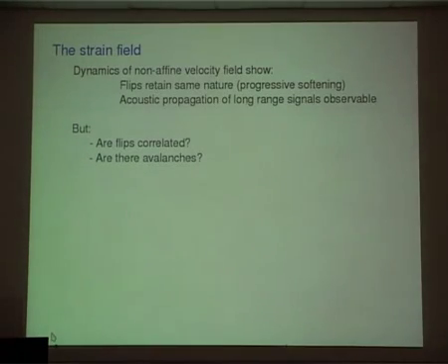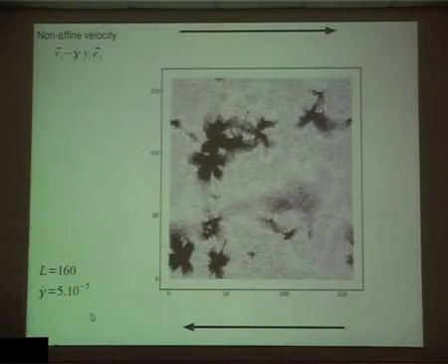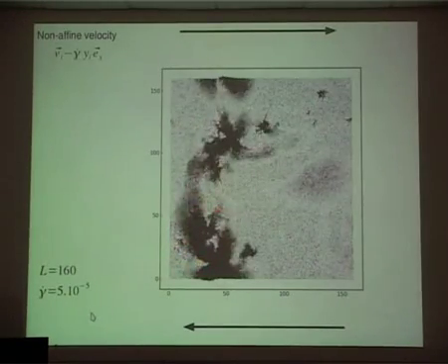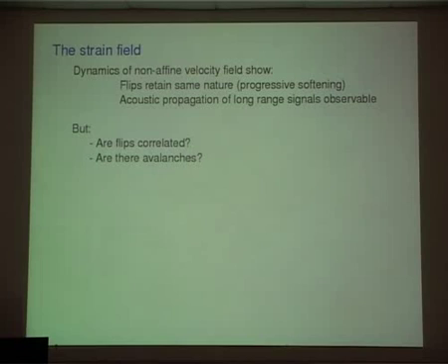So now what we see is that we continue to have the elements which were responsible for avalanche behavior. We continue to have shear transformations. We see these shear transformations, they are indeed elastically coupled. They even emit elastic sound waves. From time to time, we didn't see that maybe in the movie, but from time to time you can see that one will trigger a second one. This is something that you actually see if you look closely at this movie. So there are correlations between these events. But now the question is, do they actually make avalanche behavior? And under what conditions at a finite strain rate?